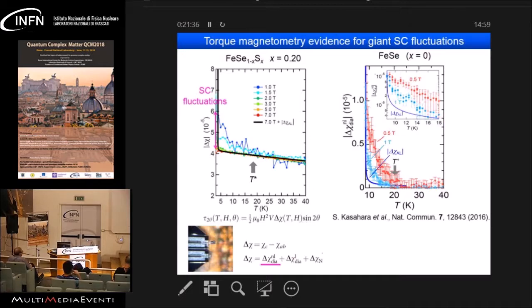Okay, so we can also measure the magnetic torque. This is again the delta chi as a function of temperature at different fields. As you can see, we see a large field-dependent component, so we have large superconducting fluctuations. This solid line is what is expected from the Aslamazov-Larkin conventional Gaussian-type fluctuation. So we have a strongly enhanced superconducting fluctuation again, and the magnitude of this deviation is much larger than in iron selenide. This is, again, consistent with the BEC-like state in the tetragonal side of iron selenium sulfur.